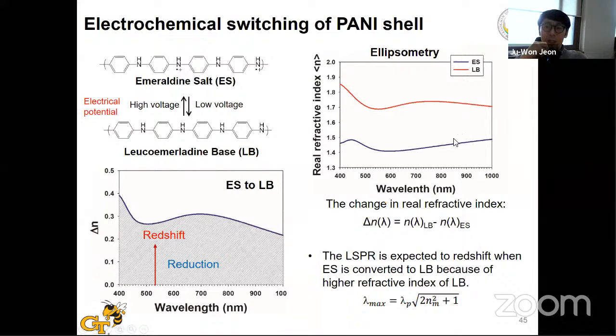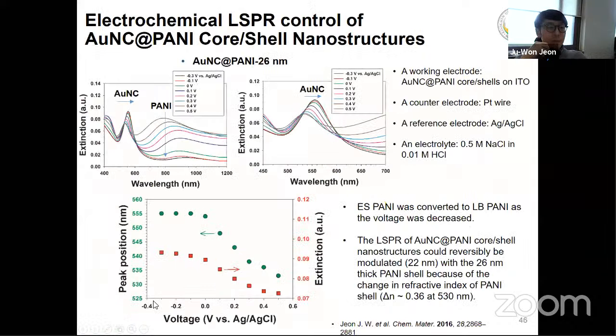So these are the refractive index obtained by the ellipsometry, and we can expect the redshift when we convert this emeraldine salt to the leucoemeraldine base because of this kind of relationship. So as expected, when we decrease the electrical potential and convert the emeraldine salt to the leucoemeraldine base, this LSPR property is redshifted as expected. So we can control the plasmonic peak position, like from 555 to 535. So 20 nanometer LSPR peak modulation is possible in this kind of gold nanocube and polyaniline shell.